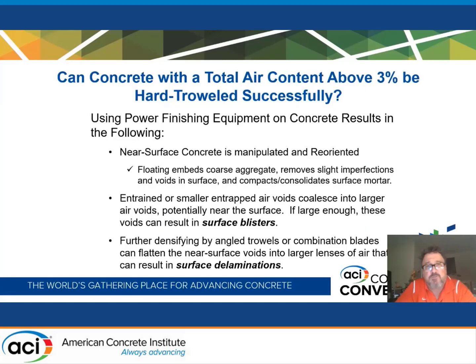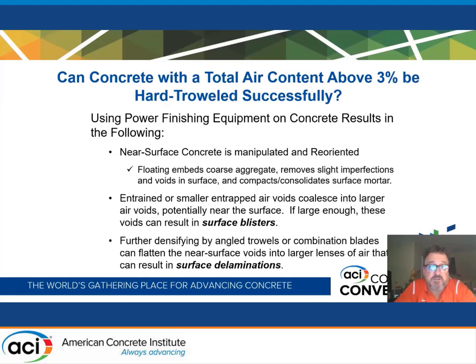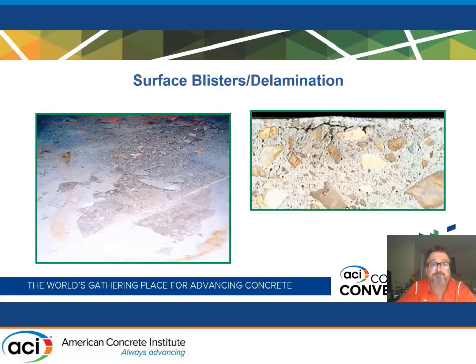The third question in the Q&A was: can concrete with a total air content above three percent be hard-troweled successfully? The answer is: not recommended. It is a risk of surface blisters and surface delaminations using any kind of power equipment. As you're floating the concrete slab, those tiny entrained air bubbles and smaller trapped air bubbles coalesce into larger air bubbles. If these end up near the surface, you get blisters. As it's troweled, these larger air voids can be flattened into lenses just below the surface that can lead to surface delamination. Any total air content above three percent increases this risk.